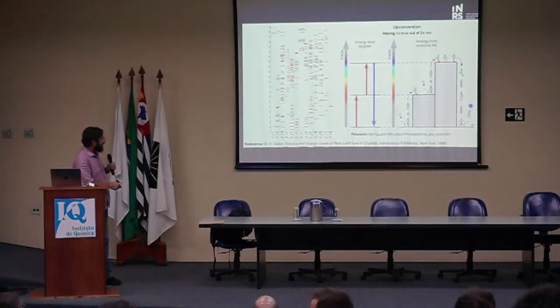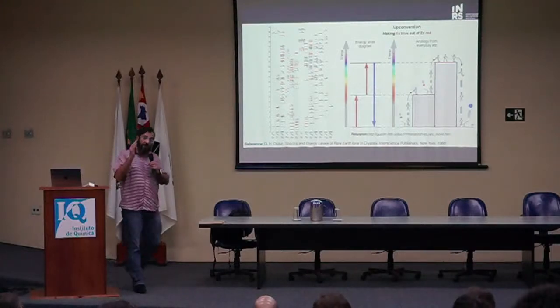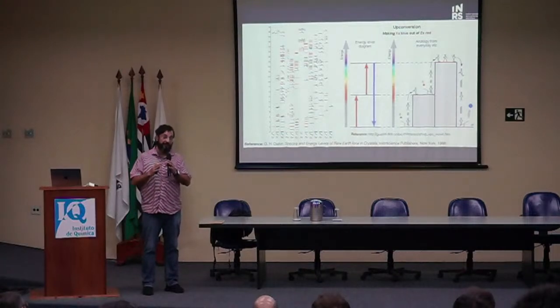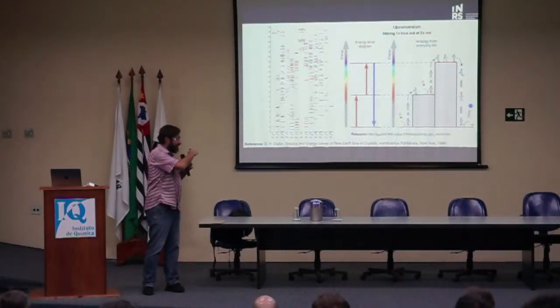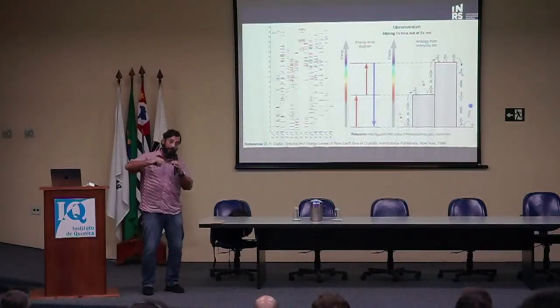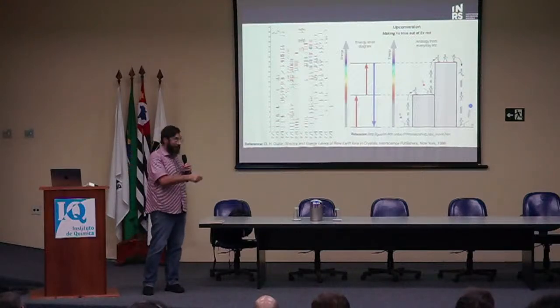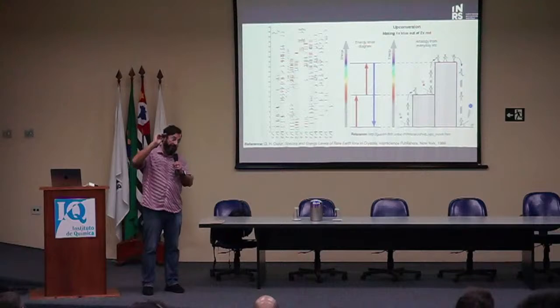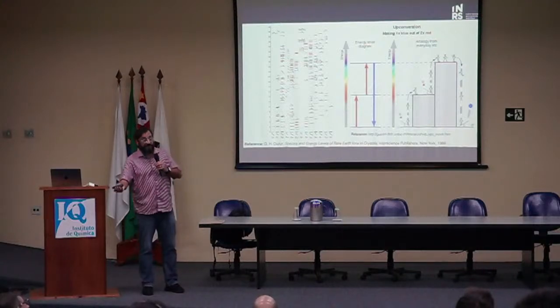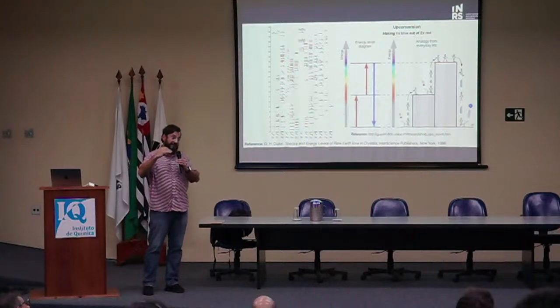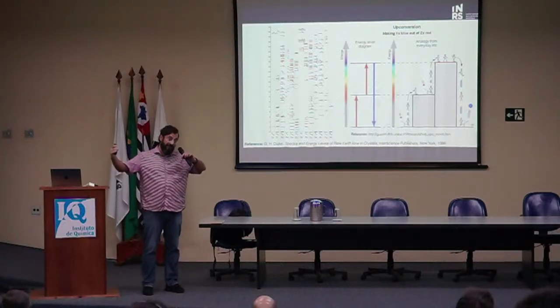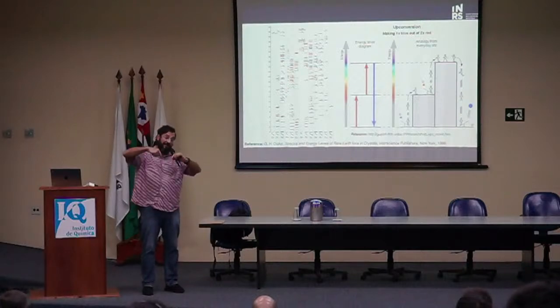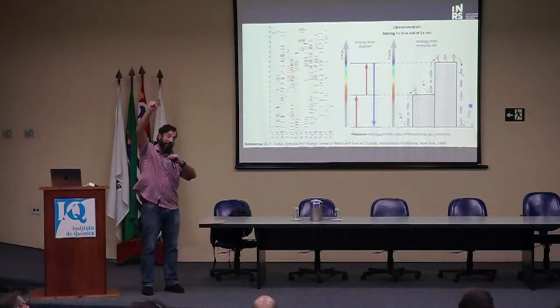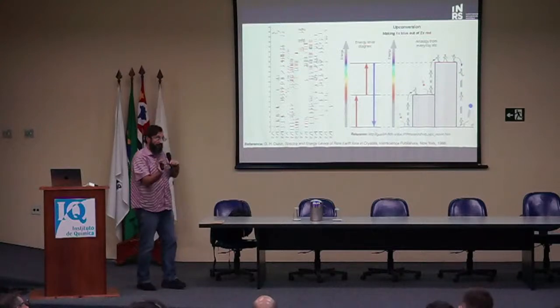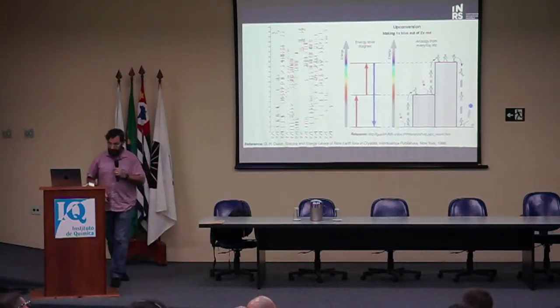Now, I should mention that this is a type of multiphoton excitation, very different from conventional multiphoton excitation that many of you may be familiar with in organic dyes or in quantum dots. In this case, these are real excited states, so it's a sequential absorption of photons, step by step, and so you can do it with a very inexpensive near-infrared laser. In other types of materials, there is no real intermediate state. So you need an ultrafast laser, like a femtosecond laser, and the photons have to arrive almost simultaneously in order to propel you to that upper state. Okay? So very different photophysics. This is much more efficient.